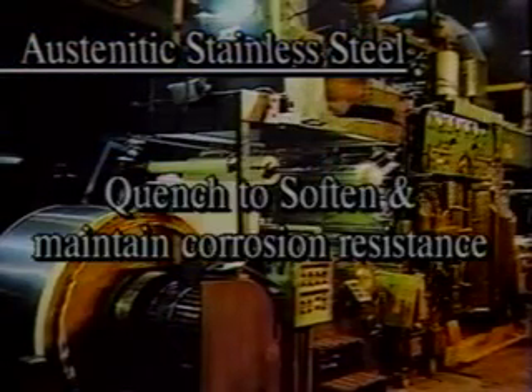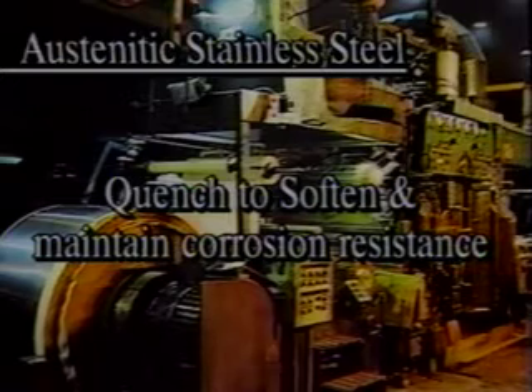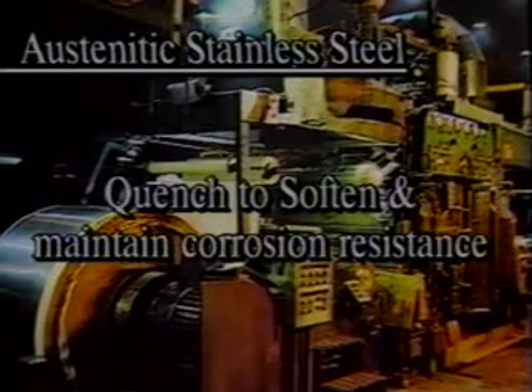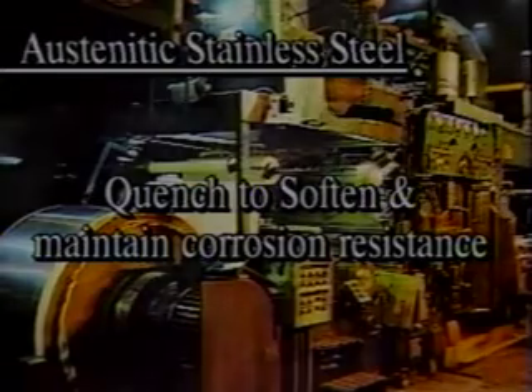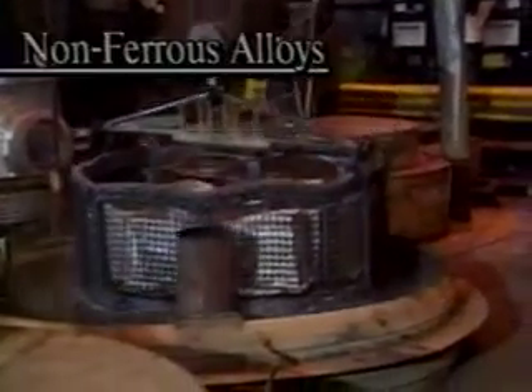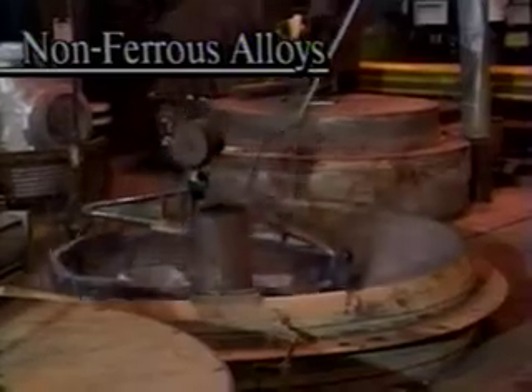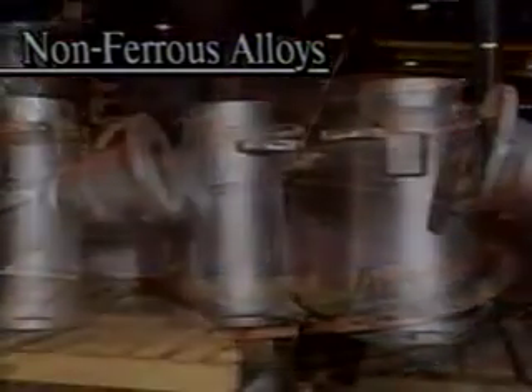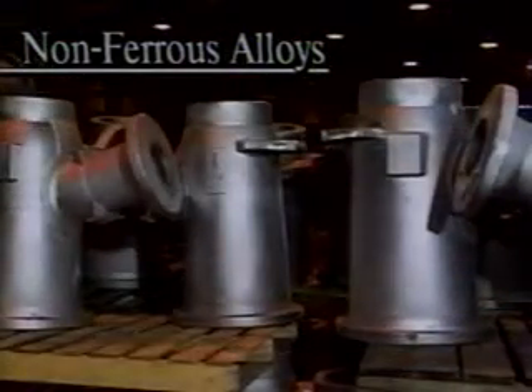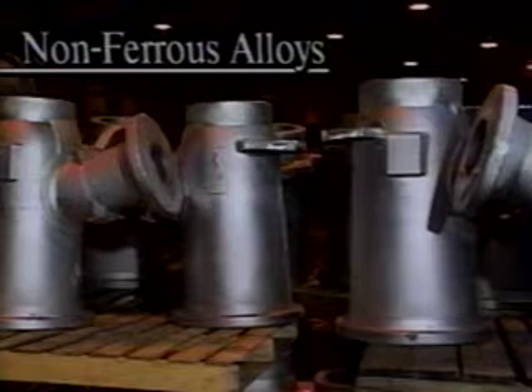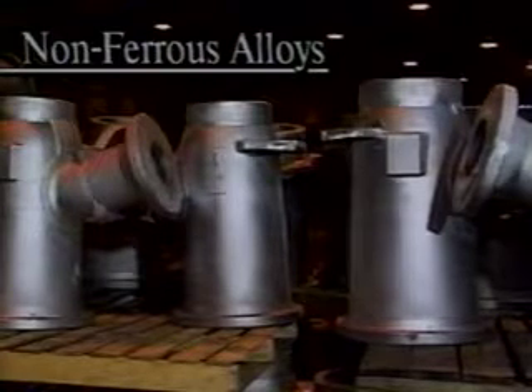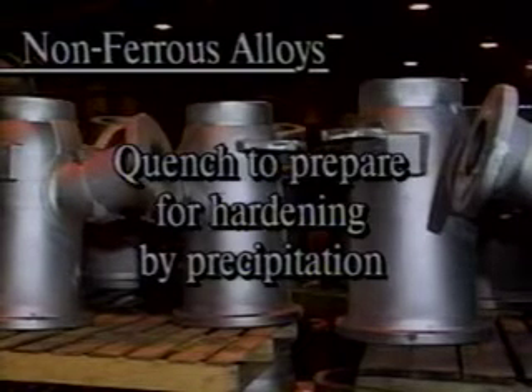These steels remain soft when quenched. The purpose of quenching is to maintain their resistance to corrosion. More about this in a moment. Non-ferrous alloys are quenched for still another reason. They are quenched from a solutioning temperature in order to retain the alloying elements in solid solution. This is a process that prepares the alloy for subsequent hardening by a controlled thermal treatment called precipitation.